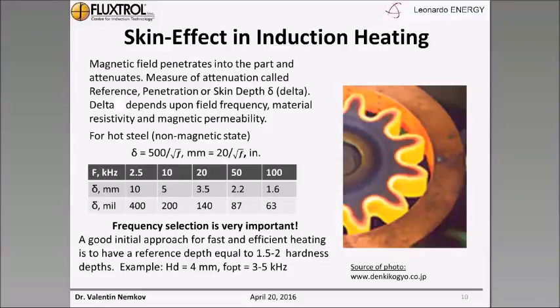The measure of attenuation is called the reference penetration or skin depth delta. Delta depends upon field frequency, material resistivity, and magnetic permeability. And for hot steel, for non-magnetic states, which is the final stage of heating for heat treating, for austenitization, the formula is delta equals 500 divided by the square root of frequency. And for frequencies widely used in the automotive industry, in a range from several kilohertz up to 100 kilohertz, this reference depth is from 10 millimeters down to 1.6 millimeters.